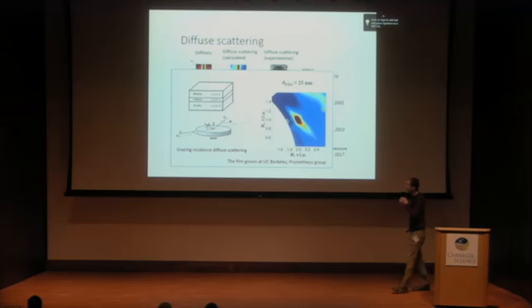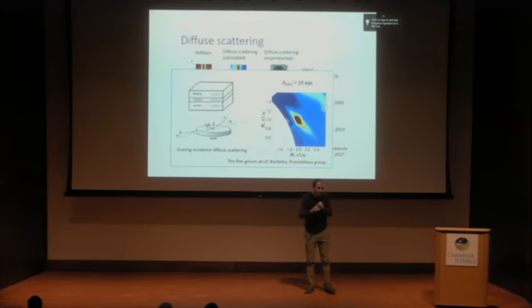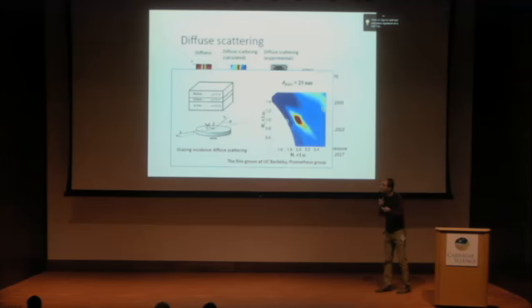In addition to that, a little drop from the experimental side. Diffuse scattering can be measured not only in single crystals, but we went further and did that in thin films. These films are of the thickness of 25 nanometers. It is very, very thin film. And still, using synchrotrons, it is possible to measure diffuse scattering in that. And temperature dependence is different, but the shape of diffuse scattering is similar, and it is consistent with what the model predicts.